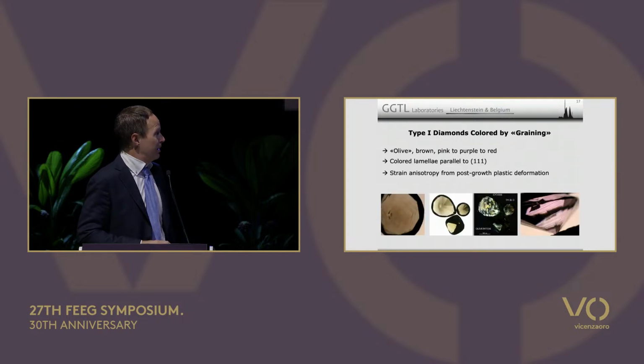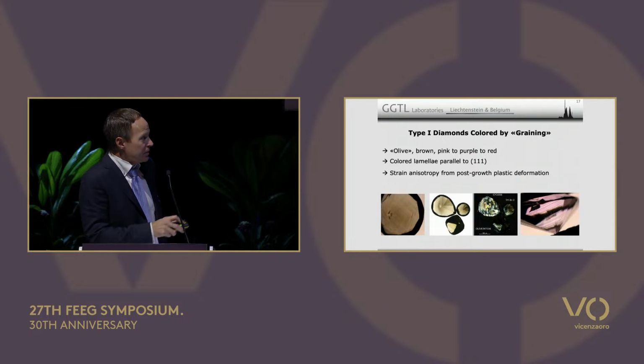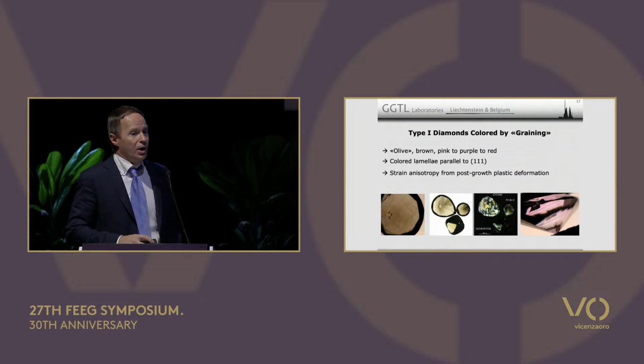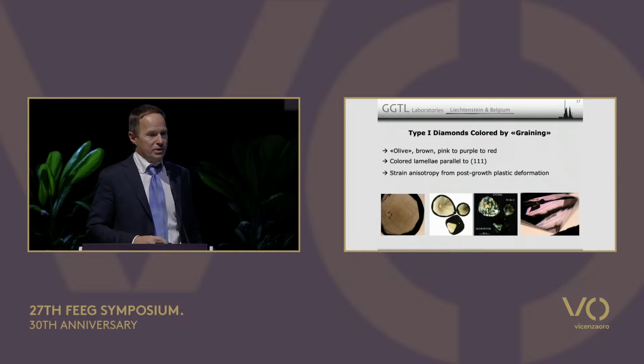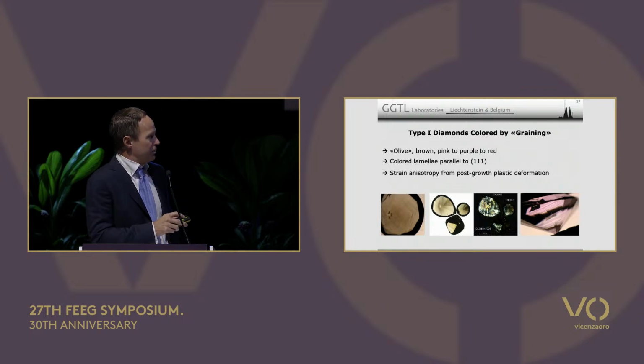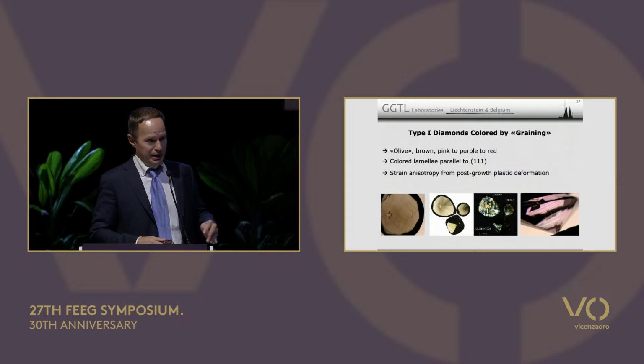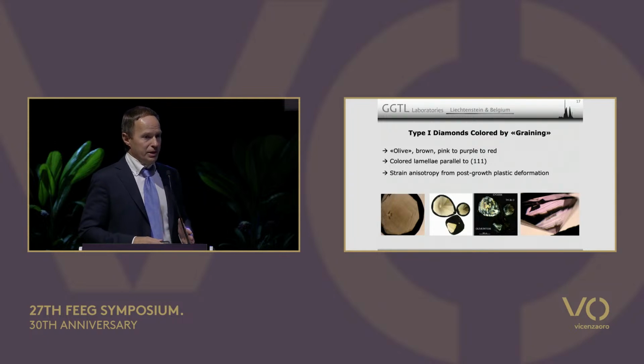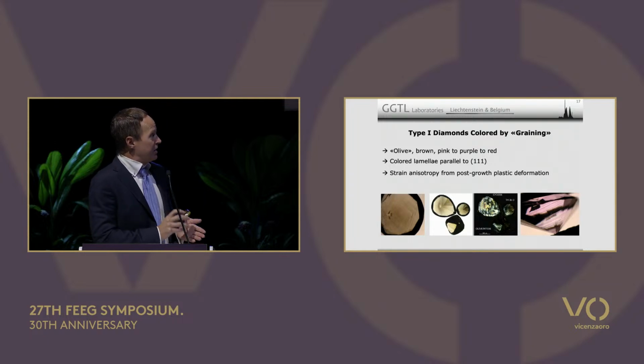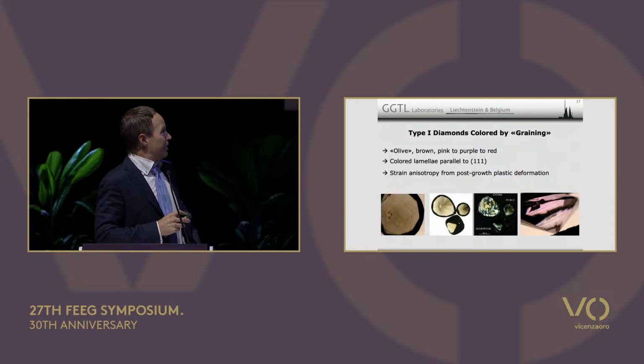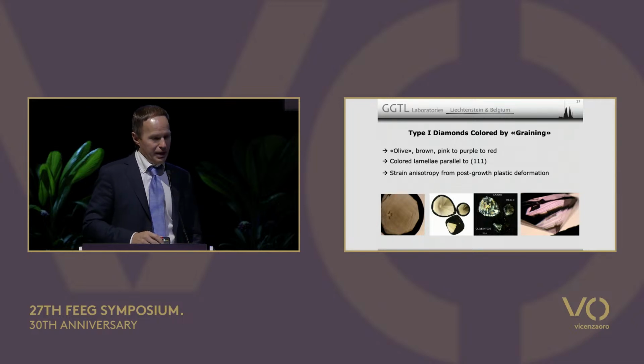These are all colored by this. So you see these funny colored lamellae traversing the stone, in brown, in olive, and in pink. And these lamellae always correspond to strong strain when you check the extinction and strain on the cross-polarizing filters, as shown here. So these lamellae are directly related to deformation, plastic deformation, slip along the octahedral direction. This is all strain and anisotropy from post-growth plastic deformation.